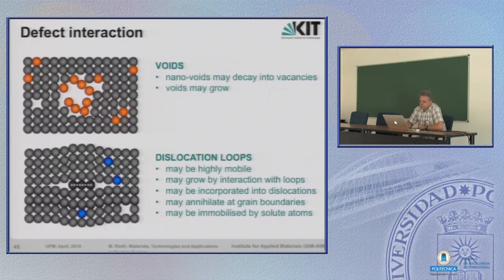Dislocation loops, that's another story. They may be highly mobile, you have seen them speeding through the lattice. They may grow by interaction, you have also seen this. They may increase their size, but they also can be incorporated into other dislocations, then they vanish in the dislocation network. They can annihilate at grain boundaries, then they are gone forever, and they may be immobilized by obstacles, by precipitates or solute atoms. This is what can happen to dislocation loops.